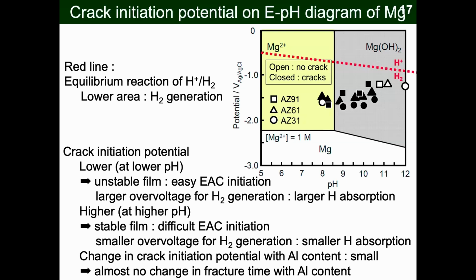And also this potential shows larger overvoltage from here. This indicates hydrogen absorption in the magnesium alloy, making it too easy to fracture. This is a hydrogen embrittlement aspect. Since the change in the crack initiation potential with the aluminum content is relatively small in this figure, therefore, we may detect no effect on the fracture time depending on the aluminum content.